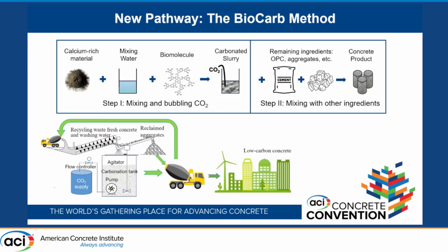Basically, the process is broken down into two steps. The first step is producing the slurry that's going to be carbonated. So like I said, you're going to have the mixing water and a partial part of your cementitious materials. And then we have the addition of a biomolecule. In this case, we're looking at tannic acid as the facilitator for this process. Then we inject the CO2 directly into that slurry. And then in the second step, we add all of the remaining ingredients and make your concrete.